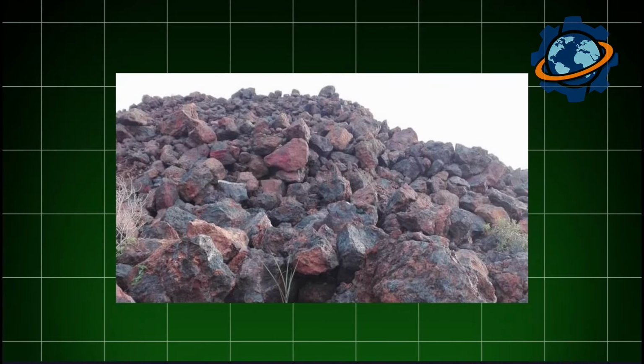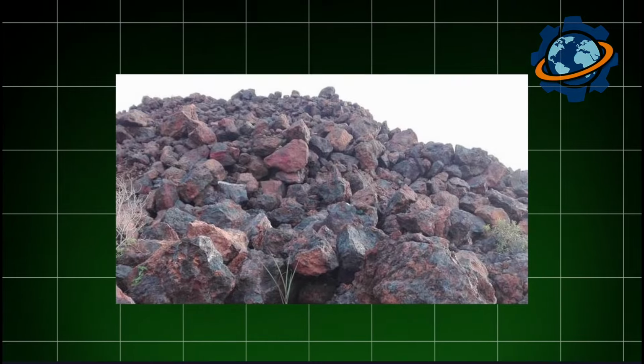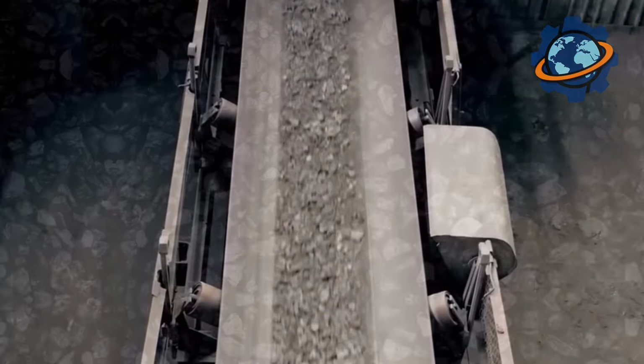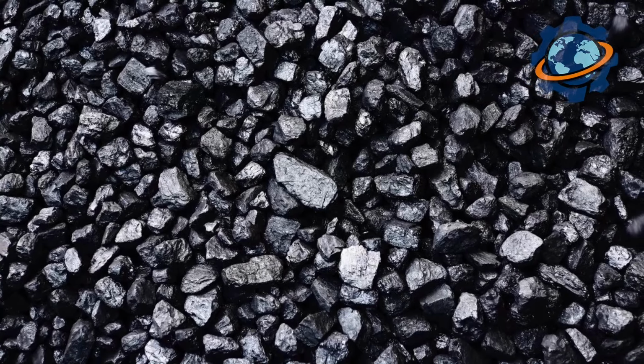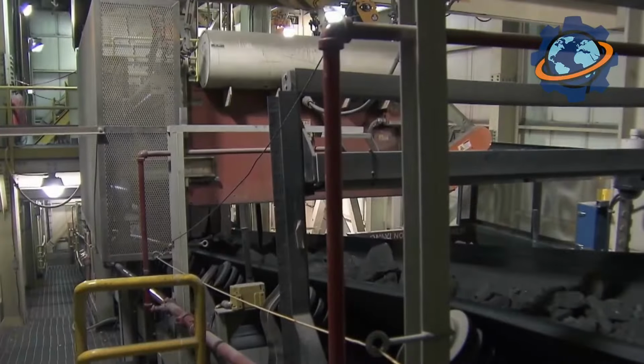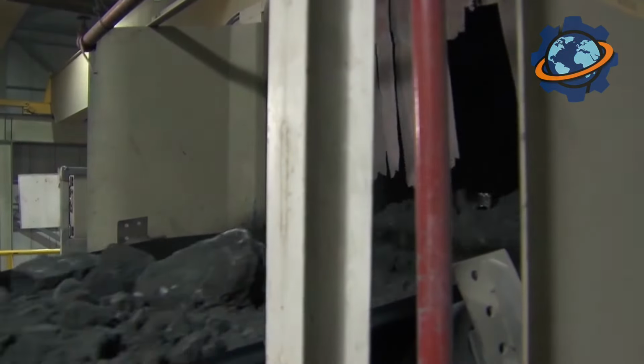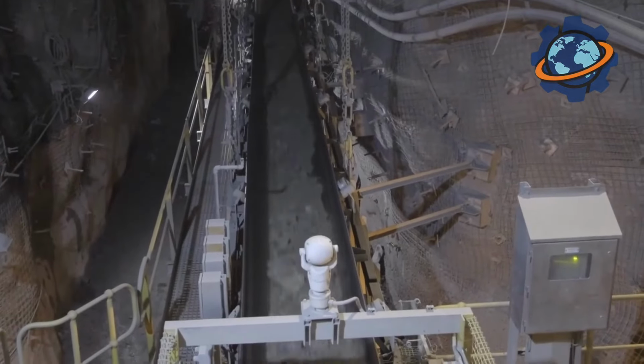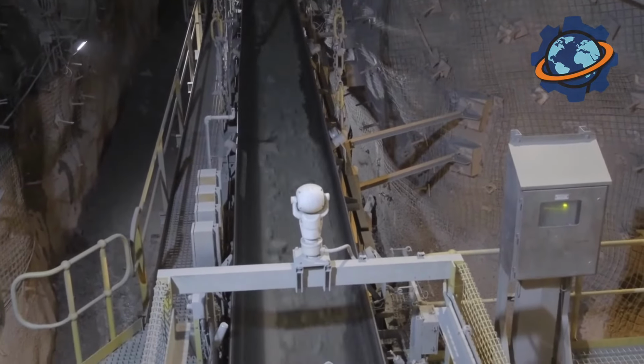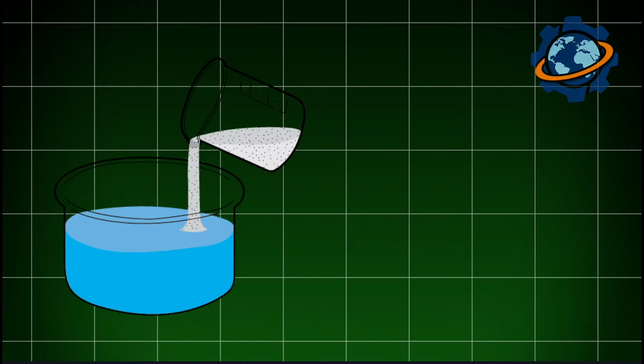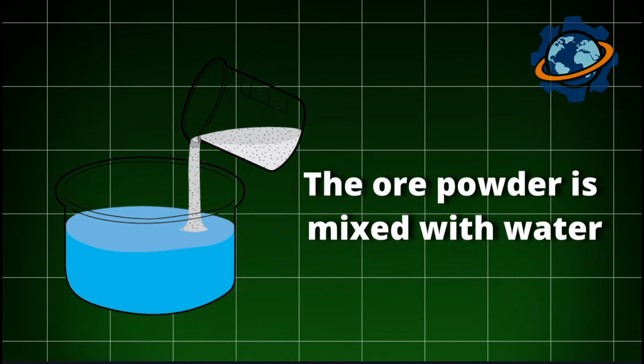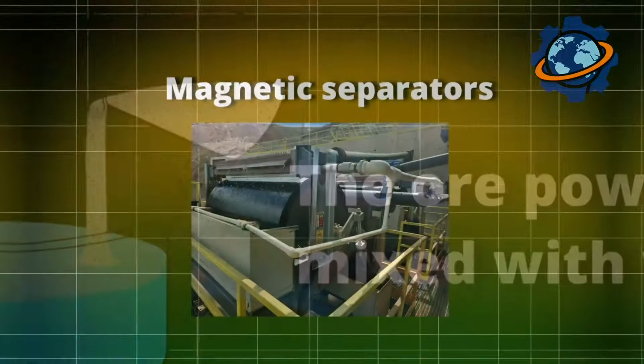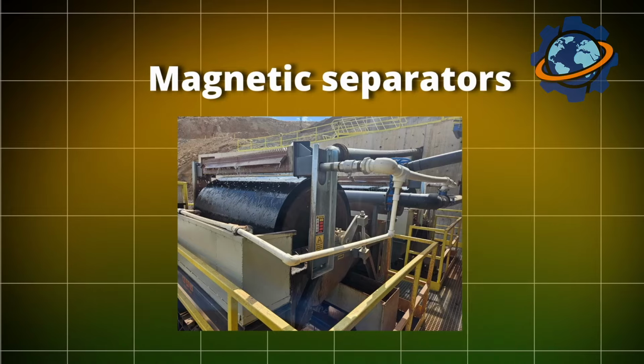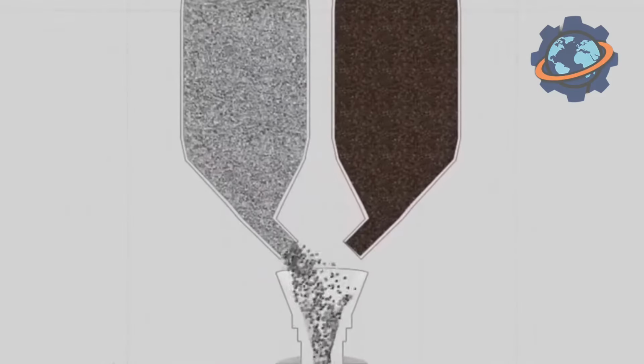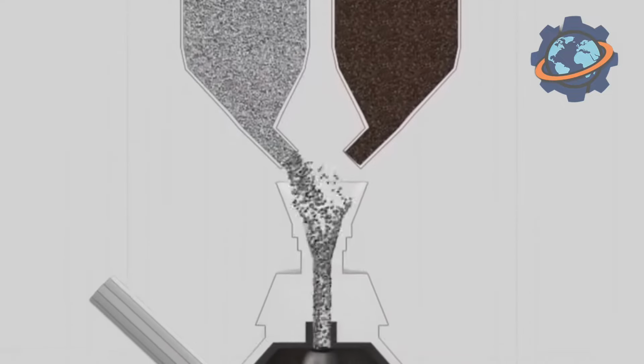It enters ball mills, steel drums 20 feet in diameter, 33 feet long. Inside are hundreds of tons of steel balls. The drum rotates, balls drop, grinding ore into fine powder. After 8 hours of grinding, you get reddish-brown dust. It's mixed with water, creating pulp, liquid slurry. This slurry passes through magnetic separators. Magnetite sticks to magnetic drums. Waste rock washes away. The concentrate contains 65 to 70% iron.